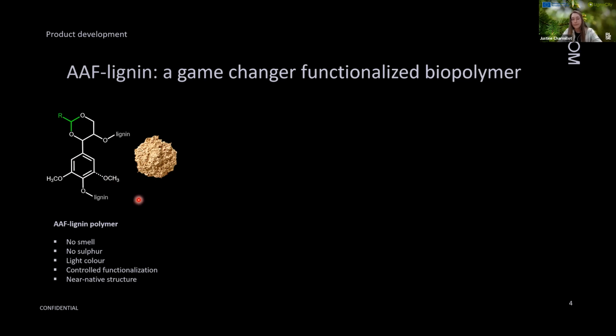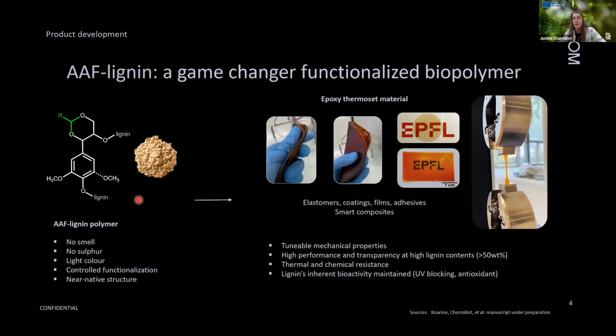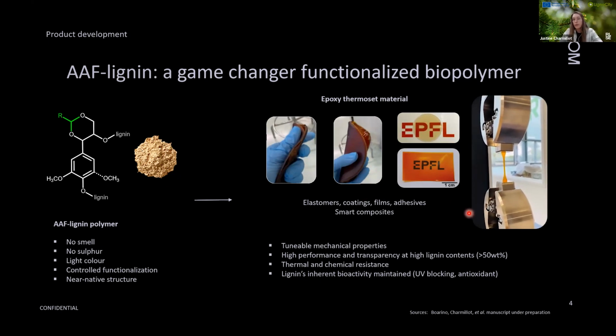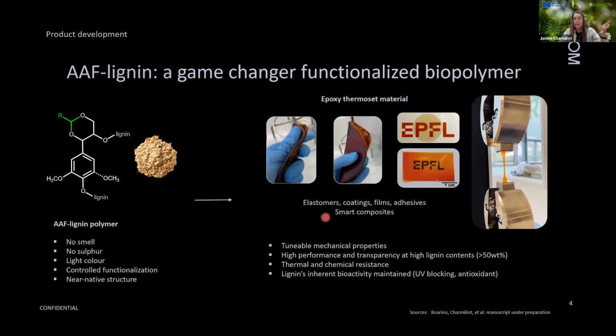that we are using. And the first application that I want to mention that we can do is, of course, use it to form epoxy thermoset materials. So those we can use to do elastomers, coatings, films, adhesives, or smart composites. As it was already mentioned before, we just take the lignin, more specifically this AAF-lignin, and we take the epoxy crosslinker, and we mix it, heat it, and we have these crosslinked materials. Very flexible, still high transparency.